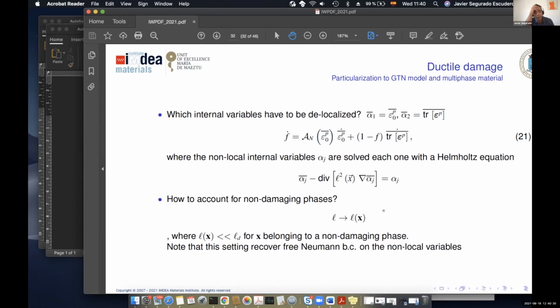From a qualitative viewpoint, you can imagine something like this. Imagine that you have an elastic phase, and you use the same characteristic length for all the RVE. Then, although the internal variable is not defined in the elastic phase, when you make the averaging through the Helmholtz equation, it will diffuse inside, because the length of the diffusion is controlled by L. If you set the characteristic length in the non-damaging phase to tend to 0, you will not diffuse inside. That's the thing. Yeah, I understand now.